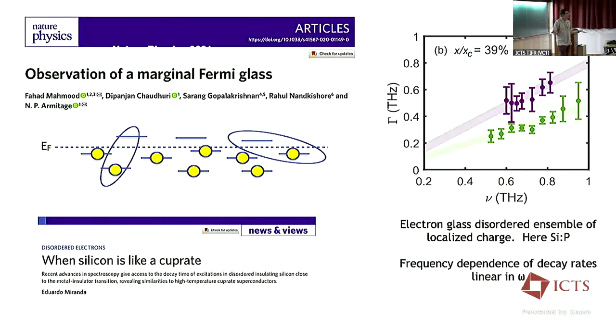The first experiments that we did, and this was done in collaboration with Rahul, was on one of my old favorites, phosphorus doped silicon on the insulating side of the metal insulator transition. And again, I won't tell you about the details of this too much, but here we think about an ensemble of localized charges, say phosphorus, doped into a crystalline background, but in such a fashion that those charges are random in space. They have a long-range Coulomb interaction with each other. This system is insulating, and at some level it's strongly interacting because there's a 1/r Coulomb interaction with every charge, with every other charge in the system.